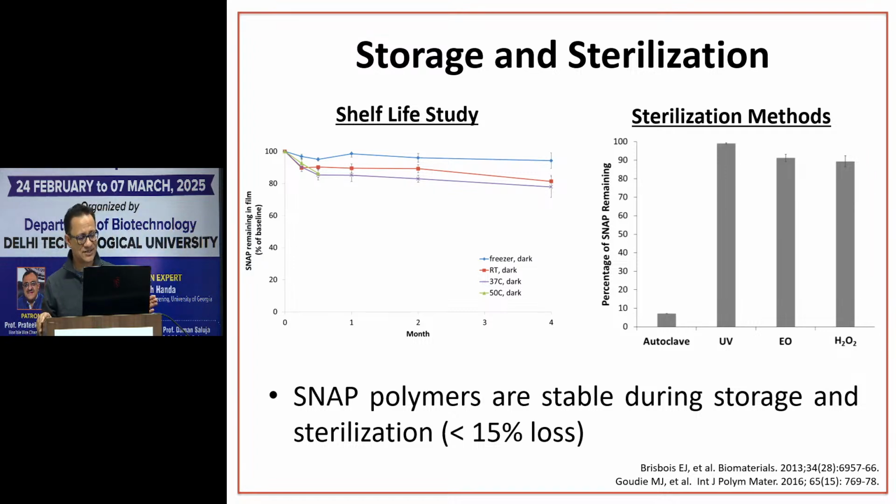We did a sterilization study. Actually, this is Marcus's paper also. He has some of this data. We tried different sterilization methods, from autoclaving to UV to ethylene oxide to plasma. Autoclaving was bad. Everything else was fine. We were able to have more than 90% NO release capabilities.